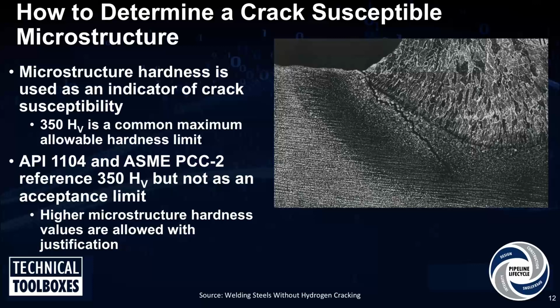All right, now, how high of a hardness are we talking about? Well, historically, one of the more common values is 350 Vickers. So the thinking back when that limit was really developed was if you have a weld that was over 350 Vickers, that weld is very crack susceptible. And if you have a hardness under 350, then you don't have to worry about cracking.